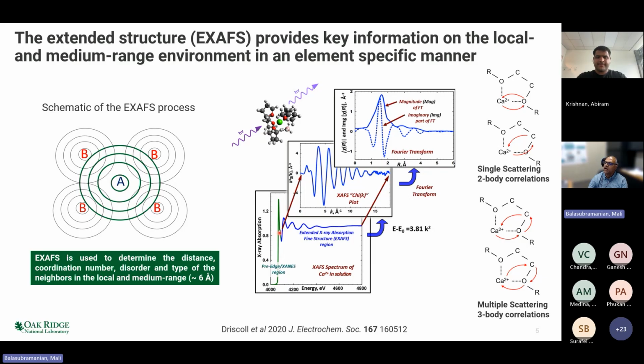And past it, say like about 20 eV above this threshold, you start seeing these oscillations which have constructive and destructive interference. So these constructive and destructive interference that you're seeing here in the absorption coefficient constitute the extended X-ray absorption region. This region has a lot of information. It's extremely rich in structural information about the central absorbing calcium atom.